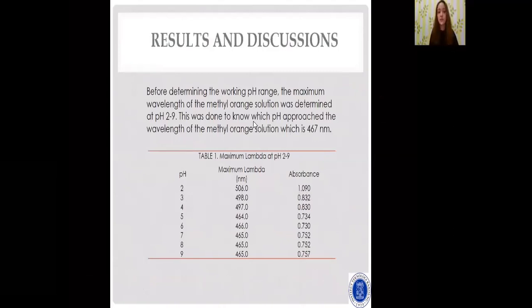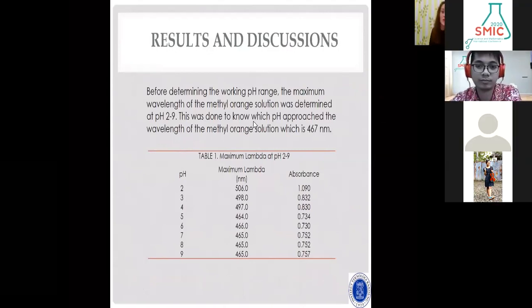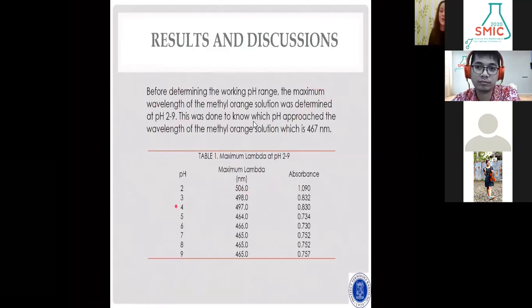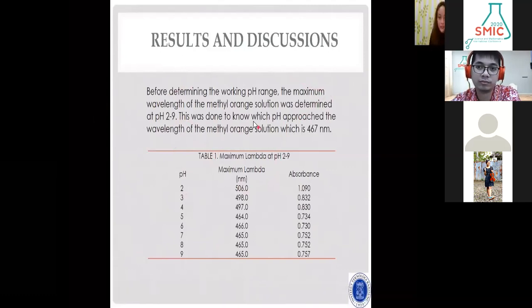So we are going to the result and discussion. Before determining the working pH range, the maximum wavelength of the methyl orange solution was determined at pH 2 to 9. This was done to know which potential hydrogen approaches the wavelength of the methyl orange solution, which is 467 nanometers. Table 1 shows each maximum lambda with each absorbance that we studied at the range pH 2 to 9. We don't count pH 2, 3, and 4 because the maximum lambda is far from the lambda maximum of the methyl orange solution.